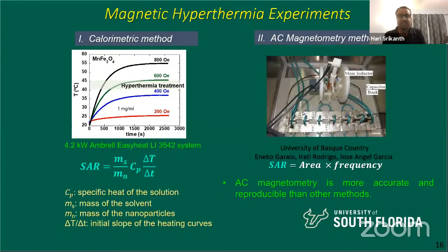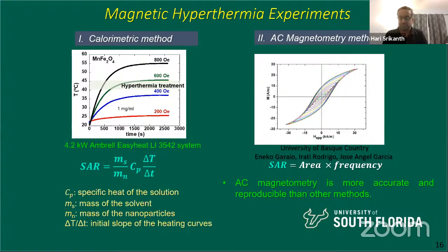We also send these particles to our collaborators in Spain, and what they do is they measure the AC hysteresis loop. They measure the entire high frequency hysteresis loop. So they built their own capacitor banks because it requires large power, and they measure the SAR by multiplying the area times frequency. So for the same particles that we make in our lab, we do 2 different experiments, and we compare the SAR and make sure that we get a quantitative match before we take it to the next stage of application, okay?